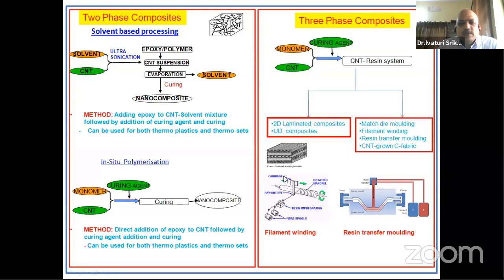But in most aerospace applications, what we talk about is around 2000 MPa, because carbon fiber, as I told, is already available as an established reinforcement. If you use carbon fiber and use an epoxy matrix, you get a strength of around 2000 MPa. So your reference is carbon fiber reinforced epoxy, not the pure epoxy. There is no application for pure epoxy. If you see the literature, 90% of it is on this kind of pure resin system added with CNT, which doesn't have any direct relevance other than to understand some basic science behind the nanocomposites.